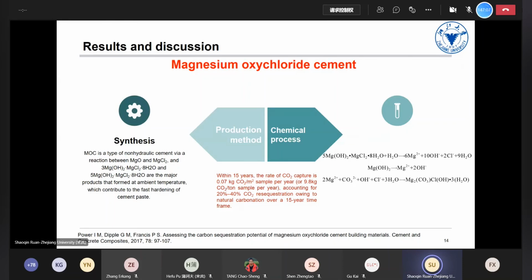There's a study showing that over the past 15 years, carbon dioxide will be further recaptured into the MOC. It is found that the rate of carbon dioxide capture is about 0.07 kilograms per square meter of sample per year, accounting for 20% to 40% CO2 resequestration owing to natural carbonation over a 15-year time frame. So this equation is about the carbonation of MOC.